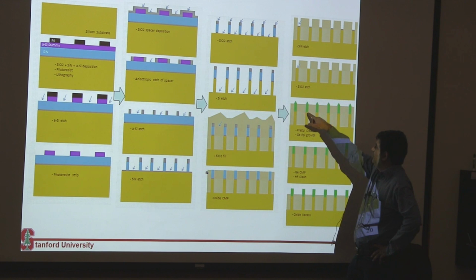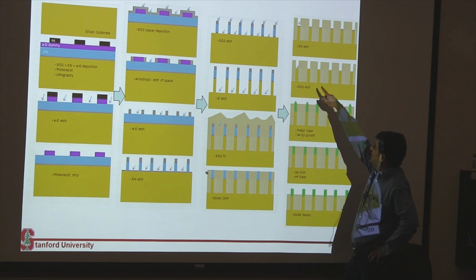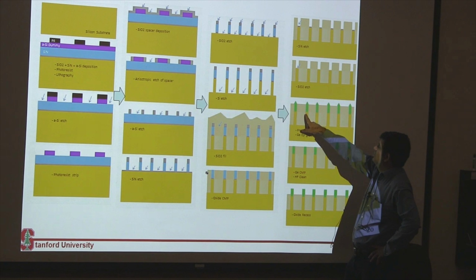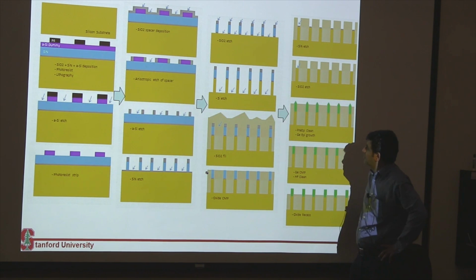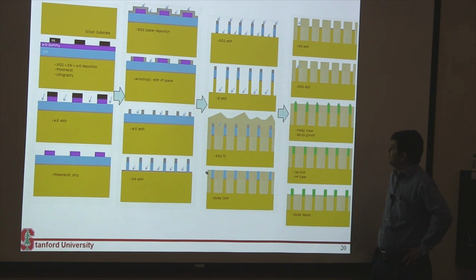And again, you do your epitaxy. You can actually do epitaxy of any material you want. So if you want to integrate other materials on your silicon wafer, this is a perfect way to do it. You make a small high aspect ratio mold, and then you can grow any material into it. It will create defects over here, but those defects would be trapped within this mold, and then your top surface would be defect free. Then you can recess this back again to the height you want, and you get these fins.